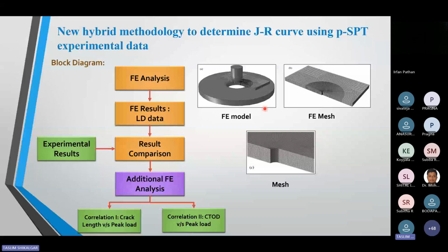I generated a similar FEA model, and here you can see this. I meshed the symmetrical model because I cannot use a 1/4 model, as I have a crack in the specimen. So I get only a half symmetrical specimen. I meshed this model, and near this crack tip I meshed using brick elements. Brick element means an 8-noded element, which I used with a full integration approach.